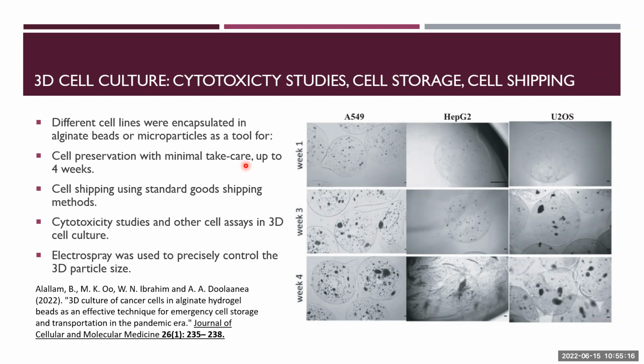when we had very limited entry into the incubators. So every student had very limited time to keep the cells and take care of them. So my student here, Batul, did this encapsulation. In this case, the cells don't need much taking care of. Up to 4 weeks, we change the media only one time per week, until the lockdown finished, or after 4 to 5 weeks, we were able to recover the cells and continue the cell culture as usual.